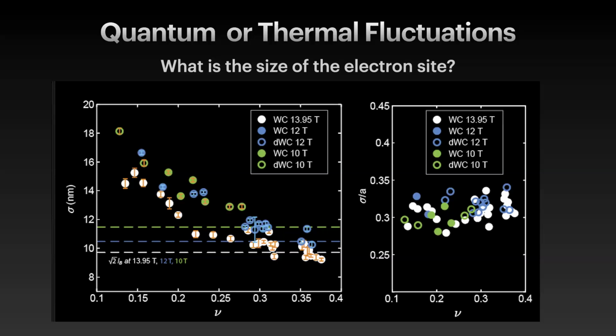Square root of 2 LB is roughly, you have 2 phonon modes. You can think of that as if the electrons are just shaking because of the zero-point motion. Interestingly, if you take this sigma and normalize it by the lattice constant, you get something like 30%. So what does this mean? It means that you have a lattice in which the electrons are localized, but they're exploring 30% of the lattice constant all the time, at least according to these images.